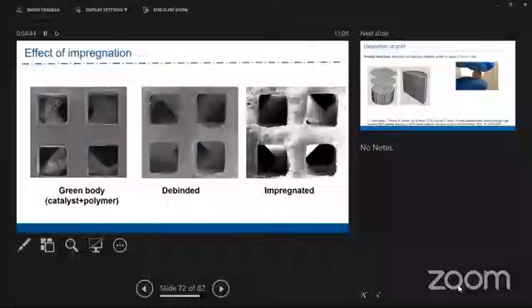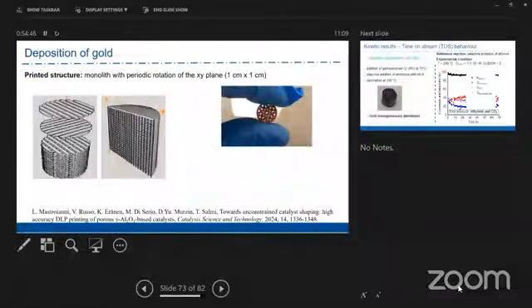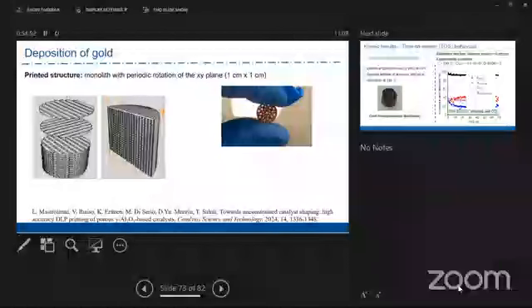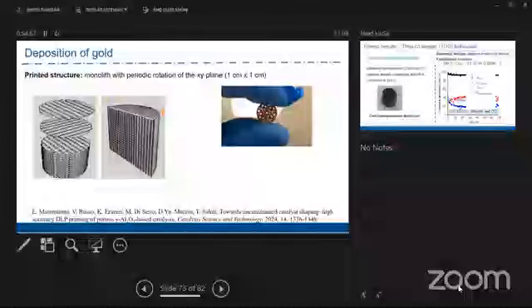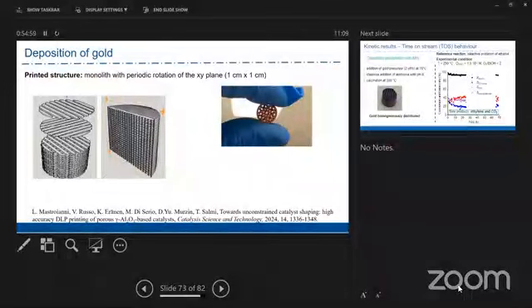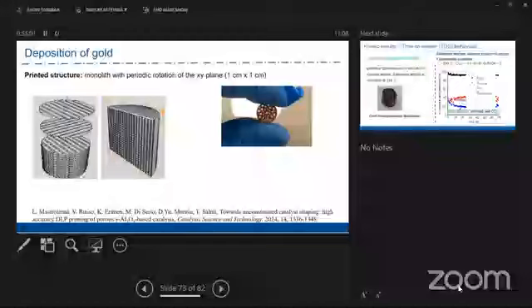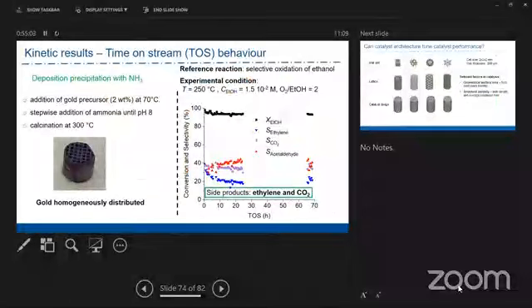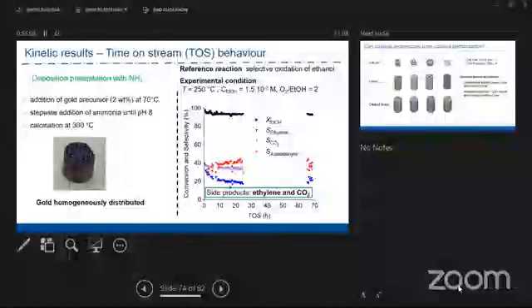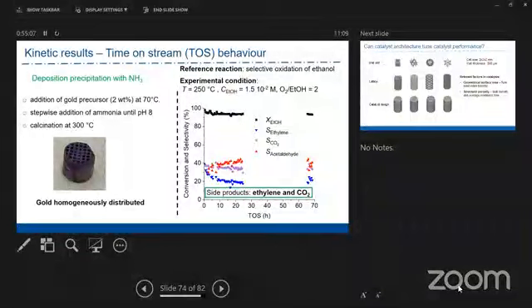So we made these impregnated materials. There are still a few slides left. So this is how it looks like. And then the next step was to deposit, in this particular case, gold. We were depositing gold on gamma alumina on the printed structures. And we did deposition and precipitation with ammonia.